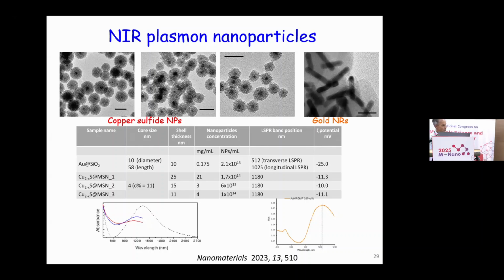And these nanoparticles produce a plasmonic effect in the near infrared. For example, these copper sulfide nanoparticles have maximum absorption at approximately 1180 nanometers, and gold nanorods have a maximum absorption at about 1000 nanometers, which is very close to the wavelengths of absorption and photoluminescence of the near-infrared dyes which we used in this work.